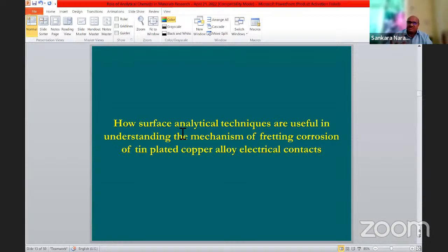Copper alone cannot be used because copper easily tarnishes by reacting with oxygen, which will increase the resistance. So they coat with tin because tin can offer good corrosion resistance for copper, and tin is highly conducting also. So normally the electrical connector contacts are like that, particularly used in the automotive industries. But the problem is, during running or during idle condition at a signal, there will be a lot of vibration in the vehicle. So what will happen? The electrical connector contacts come in contact with each other. So there will be small amplitude movement, and that leads to removal of the tin-plated material.